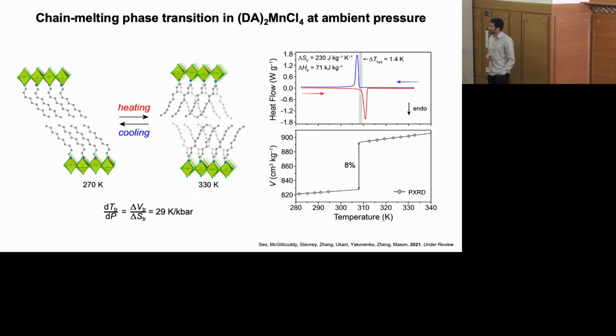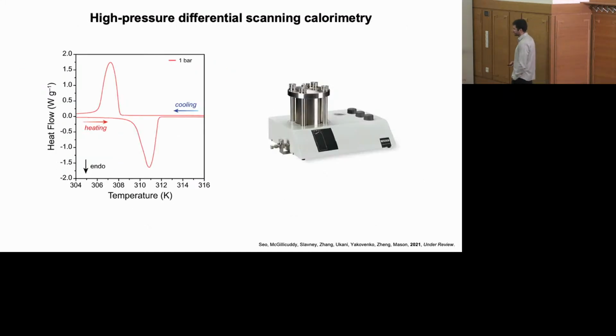And so we wanted to start exploring its sensitivity to pressure. So using just a simple thermodynamic relationship, the Clausius-Clapeyron equation, one can predict how much this transition temperature will shift as you start applying pressure. And this value was much higher than other materials that had been reported for barocaloric cooling. And so we were quite excited about that.